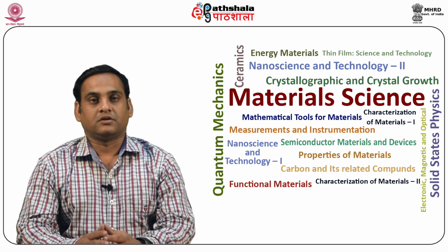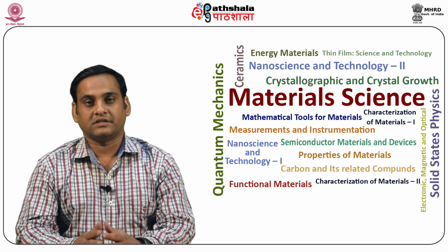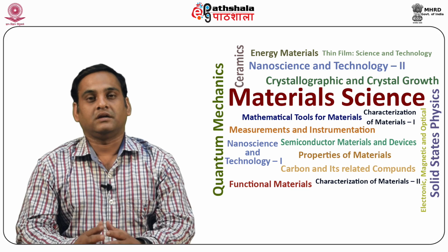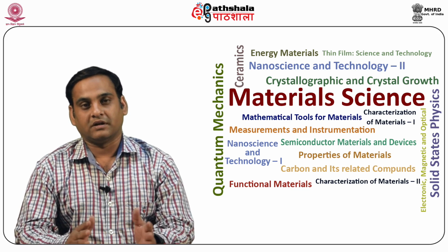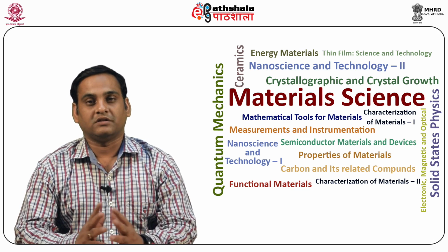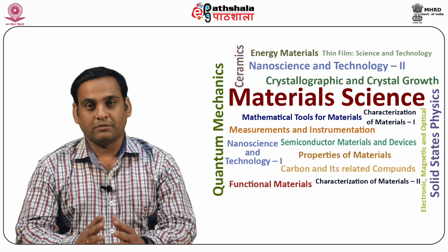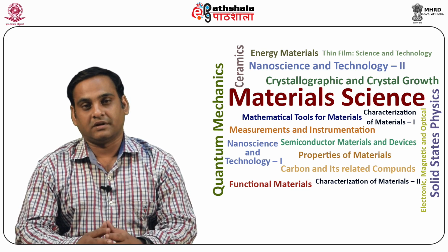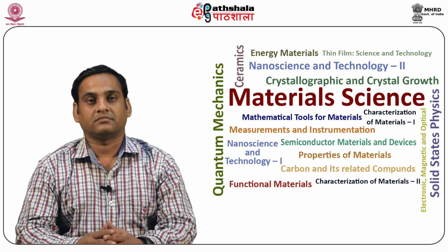Fröhlich analysis. To understand Fröhlich's model, let us take the electric field along the x axis or positive axis and suppose that the dipole can orient in only two directions, one parallel to the electric field, the other anti-parallel. Let us also assume that the dipole is rigidly attached to a molecule. The energy of the dipole is plus W when it is parallel to the field, minus W when it is anti-parallel, and 0 when it is in the perpendicular direction.